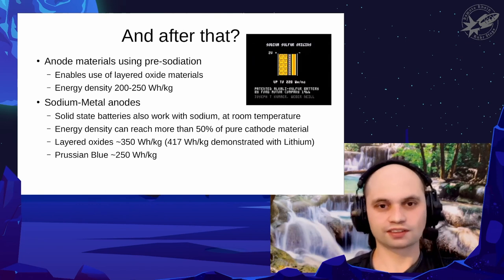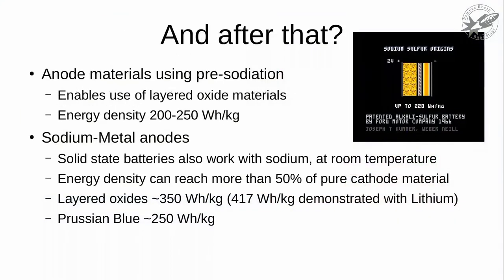So after that, what we will probably see is anode materials using pre-sodiation that can achieve higher capacity and also fewer losses in the first cycle. First cycle losses are typically about 10%, and if you can just reduce these losses by just putting more sodium in the first place, that would be great. And then you could also use these layered oxide materials that don't have enough sodium in the layered oxides at the beginning in the construction of the battery. And then you could reach energy densities between 200 and 250 watt hours per kilogram. And that would be very similar to what lithium-ion batteries have now.